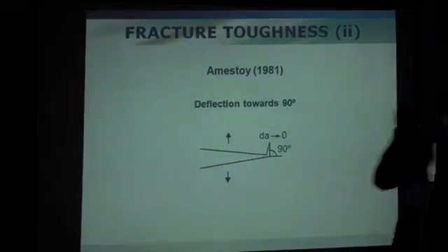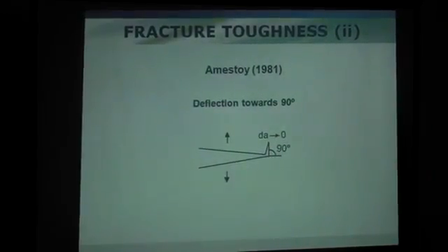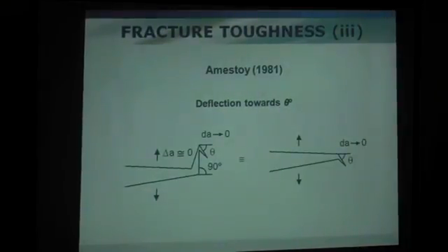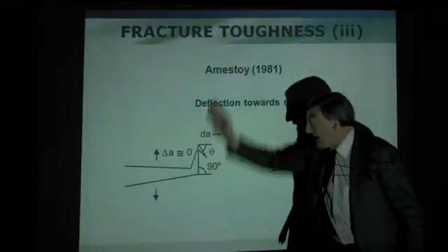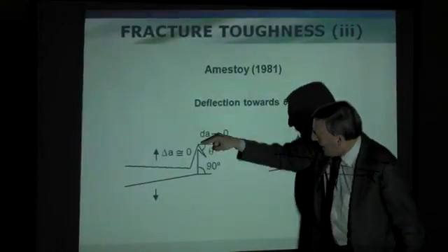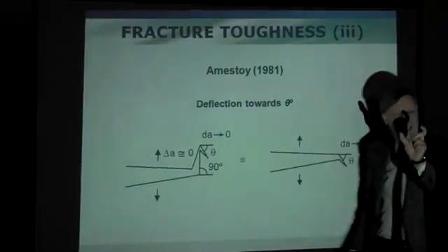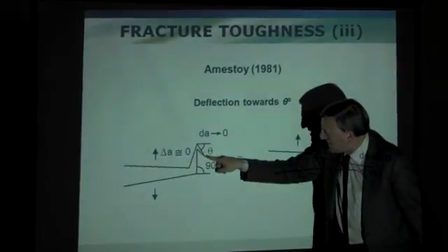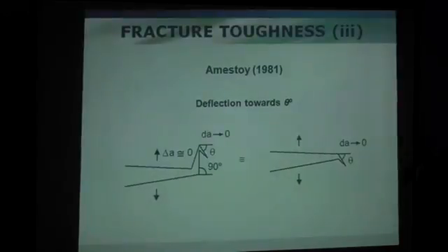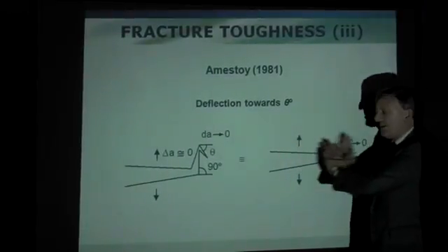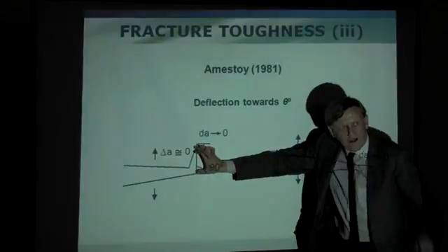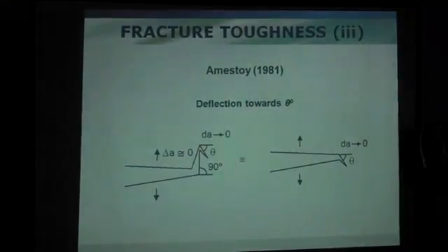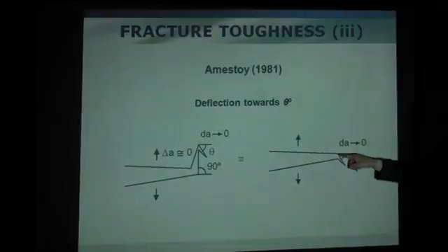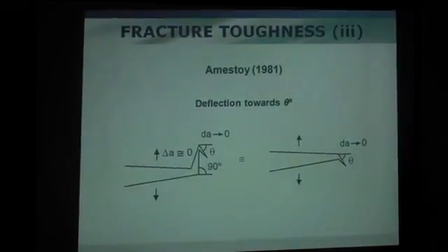We neglect this small branch, the popping of crack, delamination, the debonding, splitting. This splitting path parallel to the drawing direction, we neglect, and we consider the second branch, they are very small, the limit to zero of this angle, to obtain the directional toughness. Then, our approximation or assumption is we neglect this part, the popping, the splitting, and we consider just the branching, the deflection micro angle for initiation of an isotropic fracture.